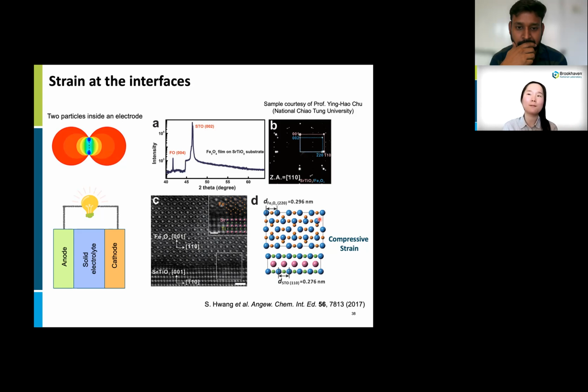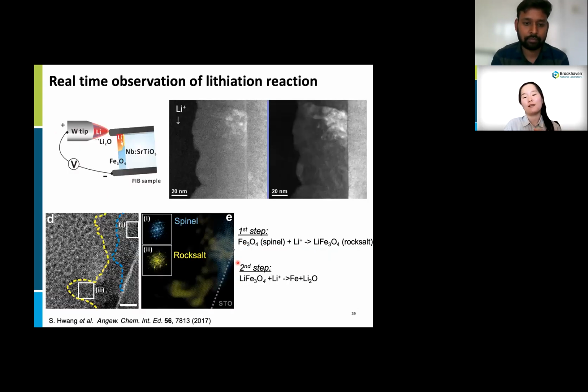So in this work, the strain effect in lithiation reaction was explored with a model system of epitaxial iron oxide thin film deposited on niobium-doped strontium titanium oxide substrate. Because of the lattice mismatch, the interface naturally experiences 7.55% of compressive strain here. When lithium ions are inserted into Fe3O4 material, first, the spinel structure is changed to a rock-salt structure based on intercalation. Then a conversion reaction follows, and as a result, iron and lithium oxide are formed.